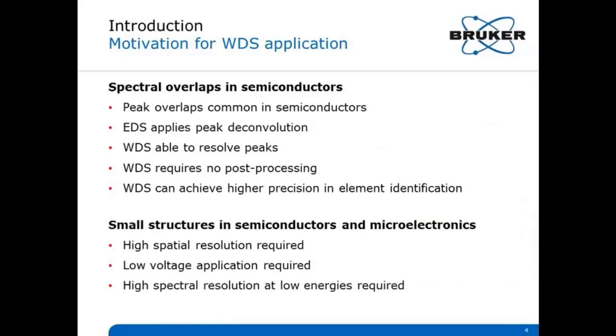Why should we use WDS for SEM when investigating semiconductors and related microelectronics? High spectral resolution, or high energy resolution, is one of the primary arguments for the deployment of WDS in X-ray microanalysis. The limited spectral resolution of EDS frequently causes serious peak overlap problems. These peak overlaps are common in many semiconductors, as we will see in the following slides. EDS tackles this problem by using peak deconvolution. WDS instead can resolve many of these overlaps. WDS thus needs no post-processing of the data such as deconvolution.